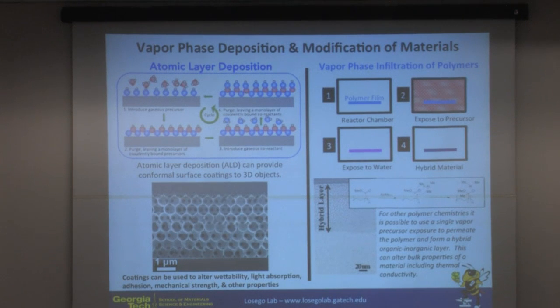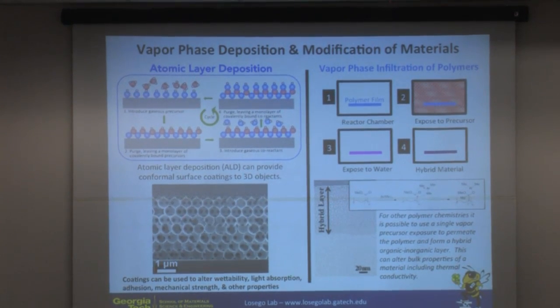The other thing that we're really interested in, this is more on the organic, inorganic hybrid materials side, is if we apply these vapor phase precursors to organic materials, to polymeric materials, they don't always behave as nicely as shown in this cartoon. They don't always just react right at the surface. Instead, they can actually diffuse into the subsurface of the polymer and generate organic, inorganic hybrid layers. And so we're very interested in the kinetics of this process. And this is one big effort in our lab, and I'm happy to talk to people about that afterwards. We're finding a lot of interesting properties with these new hybrid materials that we're creating.